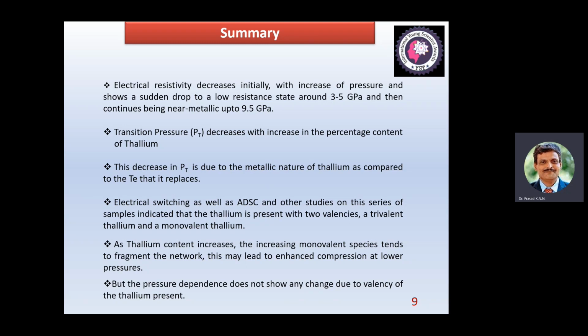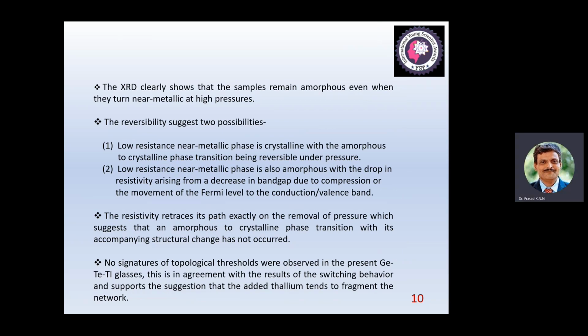Now coming to the other experimental evidences like electrical switching studies or ADSC studies, they have indicated that thallium is present with two valencies, a trivalent and a monovalent thallium. As thallium content increases, the increasing monovalent species tends to fragment the network, and this may lead to enhanced compression at lower pressures. But another point we observed is that the pressure dependence does not show any change due to the valency of thallium present. The XRD clearly shows that the sample remains amorphous even after applying and taking back the pressure.